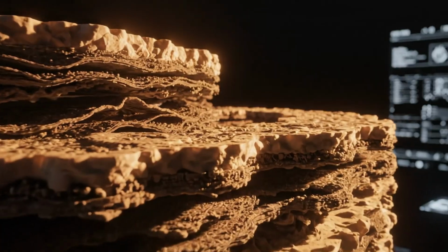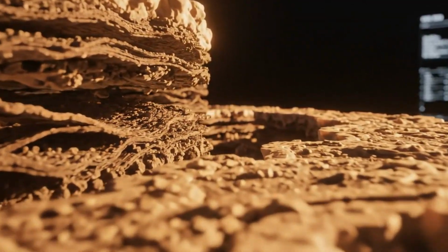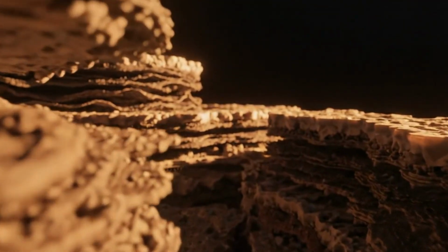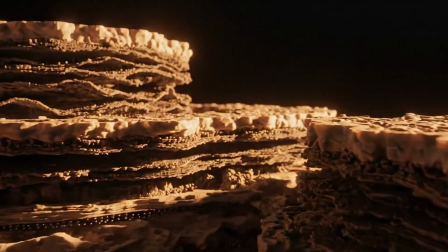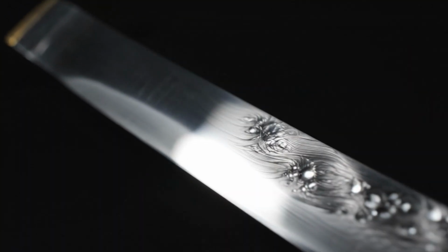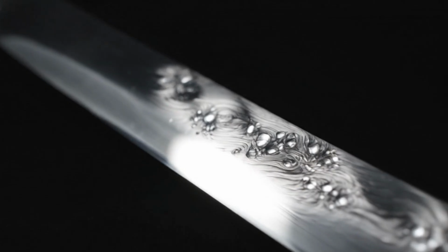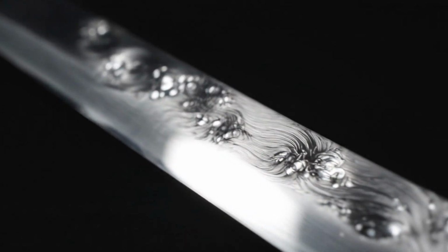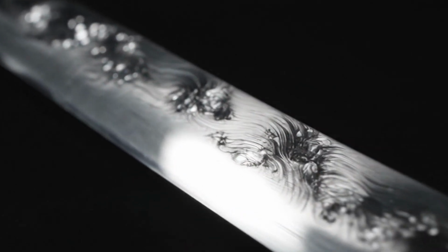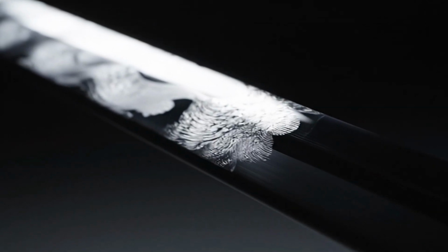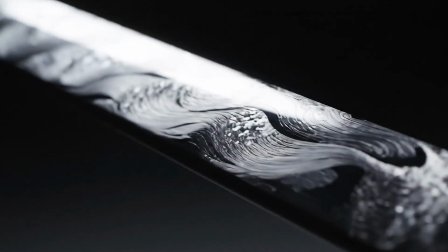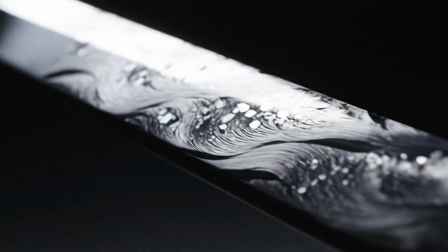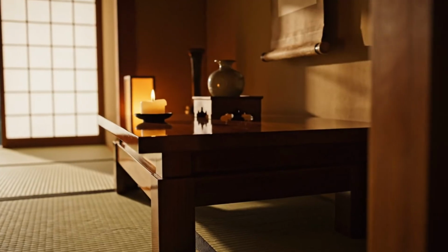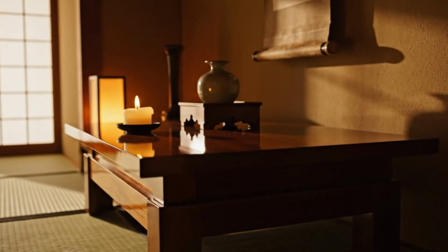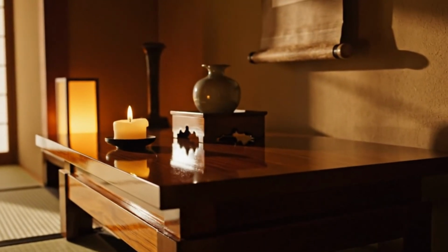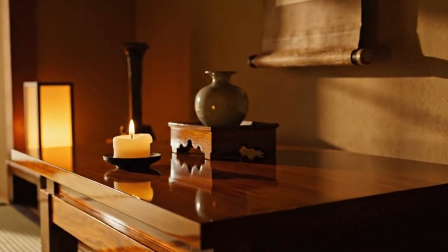Its crystal structure shifts into a phase called pearlite, a lamellar mixture of ferrite and cementite that is far tougher and more ductile than martensite. The two phases coexist within the same continuous piece of metal, joined at a transition zone that is visible to the naked eye as the hamon, the distinctive wavy line that runs along the blade and is one of the most recognized visual features of the Japanese sword. The hamon is not decoration. It is the boundary between two fundamentally different materials that happen to share the same molecular iron backbone. It is the swordsmith's signature, written in crystal structure.